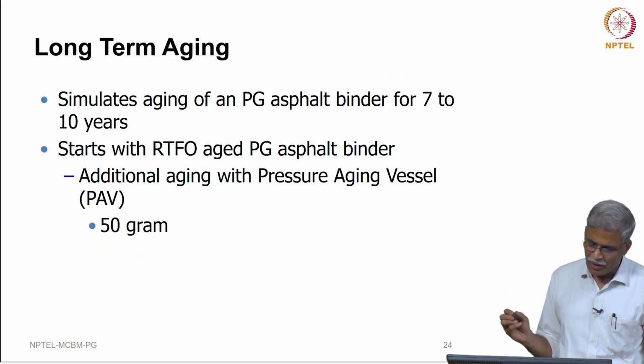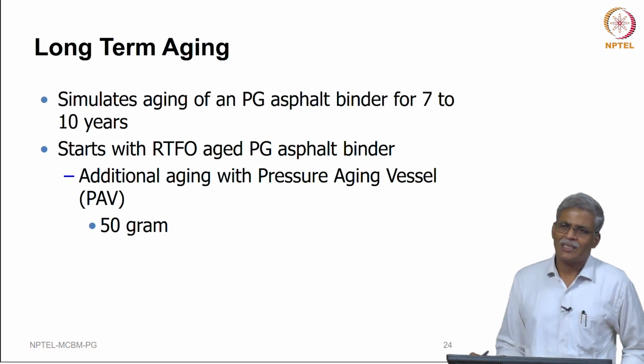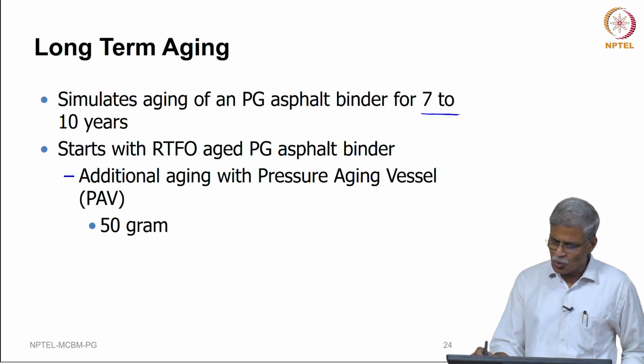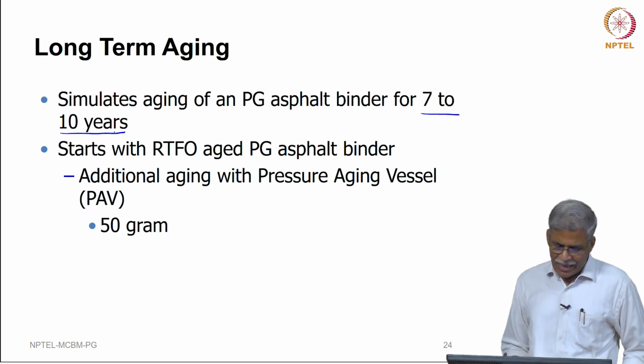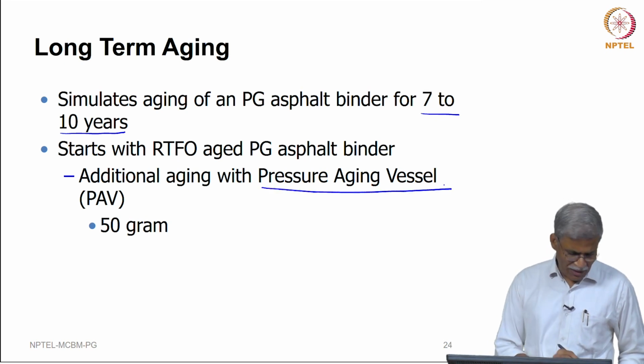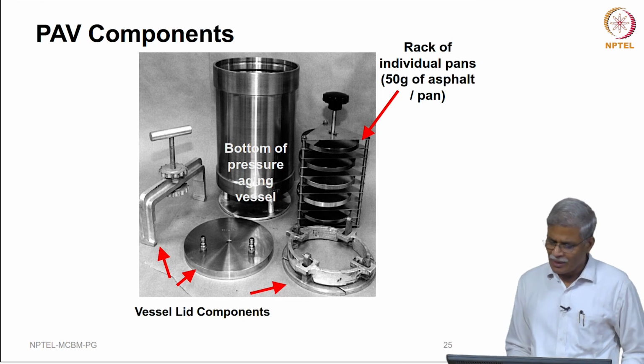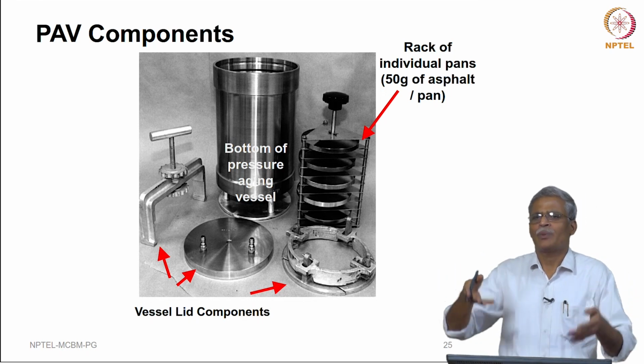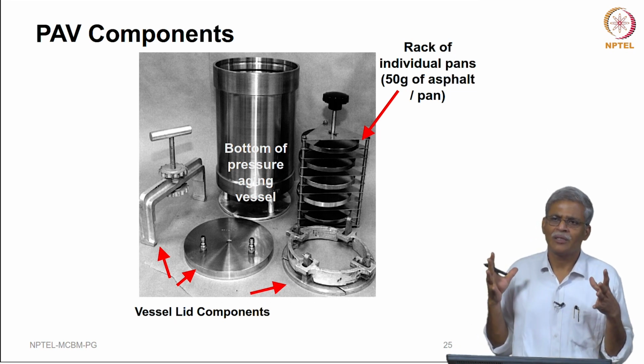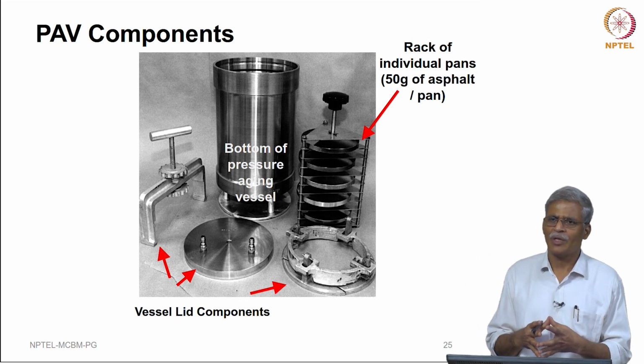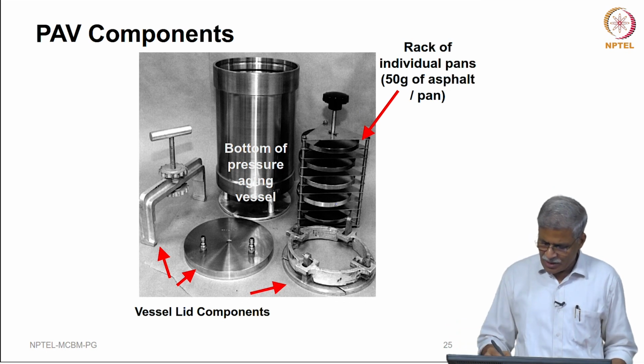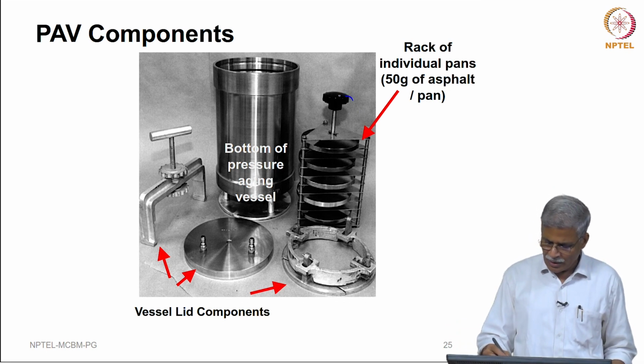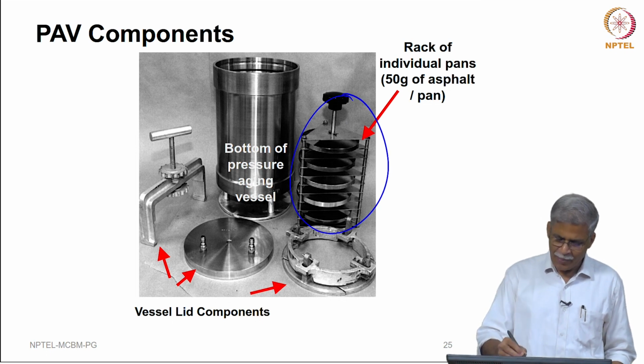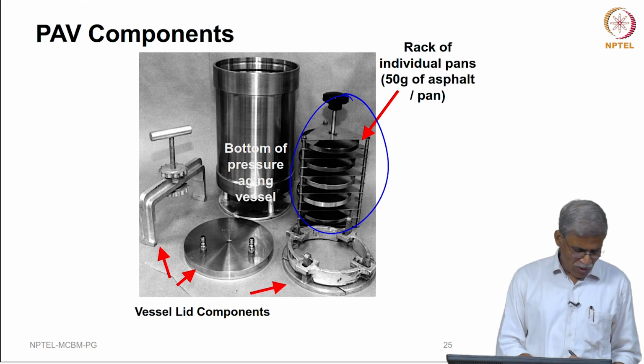Okay. So, this long term aging, again let us take a short detour here and understand what it is. This is going to simulate 7 to 10 years, and you need to do it with a pressure aging vessel. A pressure aging vessel looks something like this, and in fact, it is nothing but a pressure cooker in which you can maintain the required pressure at a required temperature for a fixed duration of time. You can see these trays shown here, which are kept inside, and the whole thing is subjected to very high pressure.